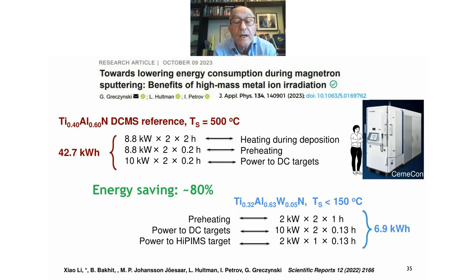Now, the blue estimate downstairs is that we are preheating at a much lower temperature. Then we turn off the heat, and for 1 hour the temperature goes down to, let's say, 50 degrees. And then we start the same DC power, but also we add the power of the target, and it ends up at like 7 kilowatt hours. So this is an energy saving of about 80%, which is the subject of a few papers by Xiao Li, a part of her thesis. And also time for shorter cooling down and shorter preheating. The next slide.